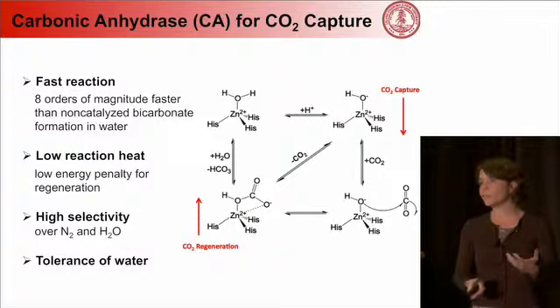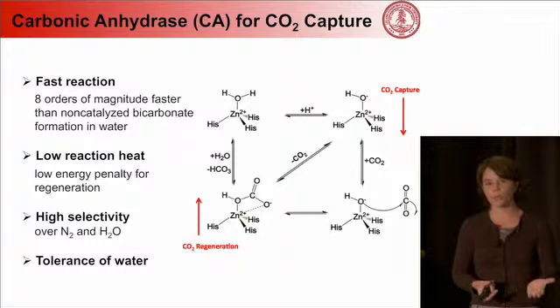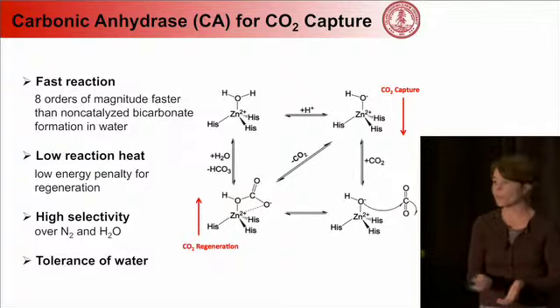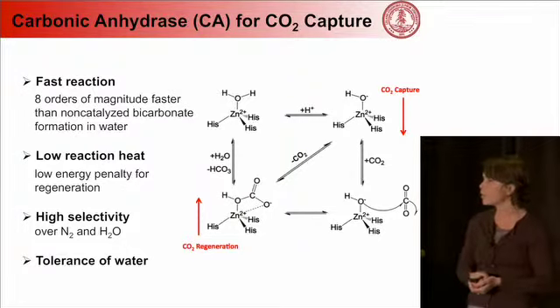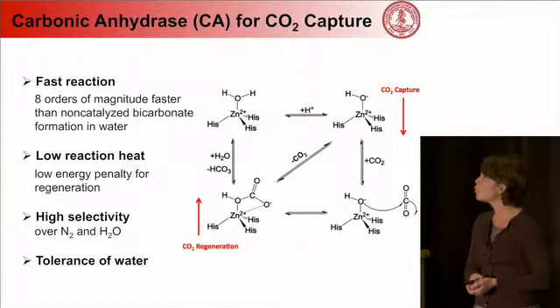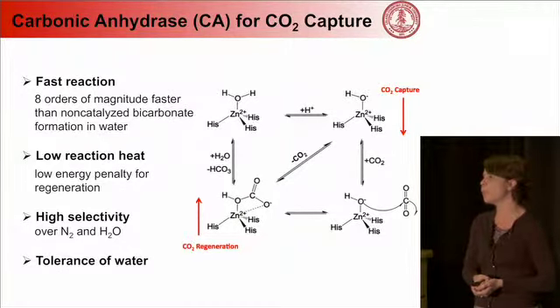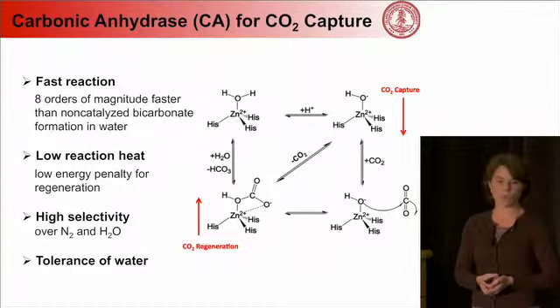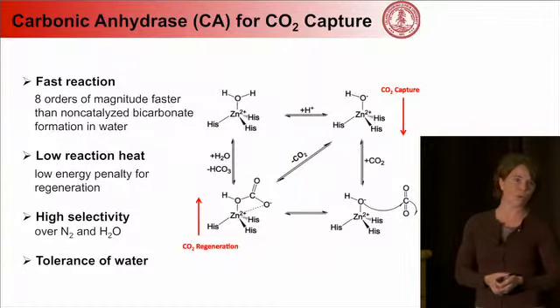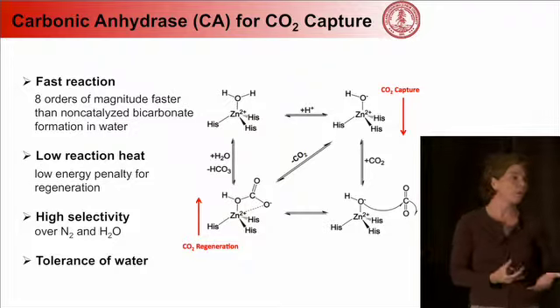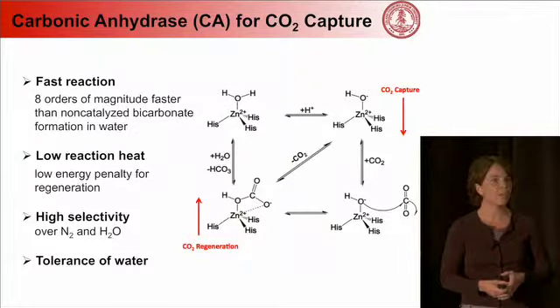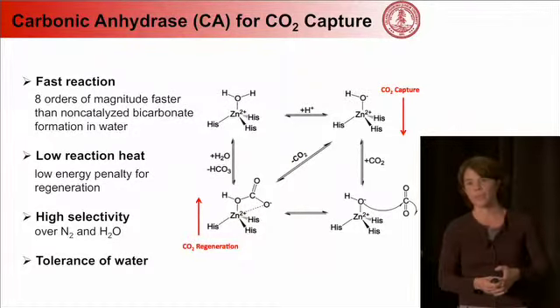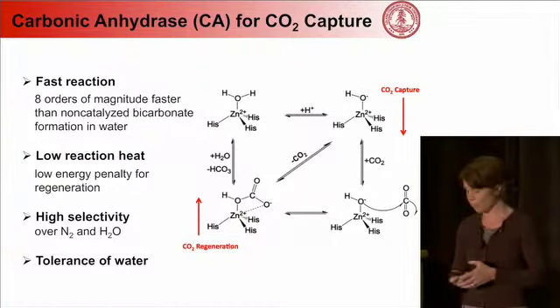If you look at CO2 dissolution in an aqueous phase, and you were to add, say, carbonic anhydrase to that mixture, you could speed up the reaction by up to 8 orders of magnitude. So this was something that we thought would be interesting if we could put carbonic anhydrase on a substrate to try and enhance the kinetics of the CO2 uptake. And this was the basis of our idea.